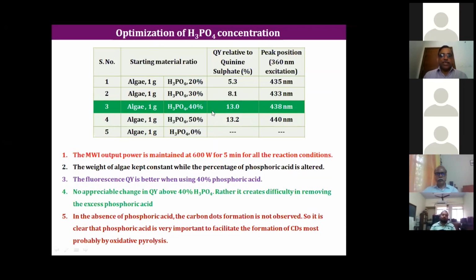So we could see that at 40% of the phosphoric acid, we get a very good quantum efficiency of almost 13%. We adopted microwave power of something like 600 watts, 5 minutes for the reaction condition, and the weight of the algae was kept constant. Quantum efficiency is better at 40%, you can see that from the data.